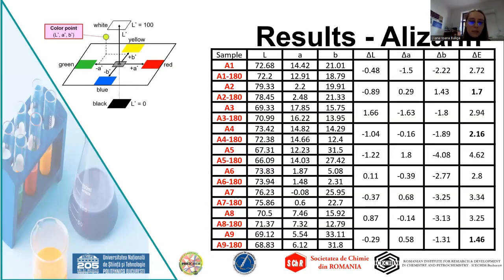In the case of alizarin, the light fastness has better results than for the other natural dye, with the lowest delta E being recorded for samples A2 and A9. It is important to notice that almost all samples here have a hue difference value below 4, which implies good resistance to light.